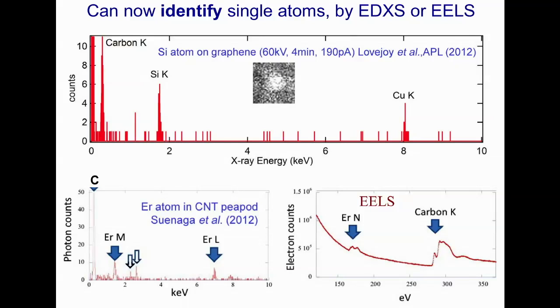The X-ray and energy loss spectra at the bottom were recorded from a specimen containing erbium atoms, each enclosed within a C82 fullerene molecule. These molecules were in turn encased in a single-wall carbon nanotube to form a so-called peapod structure. The purpose of the double encapsulation was to ensure that an erbium atom would remain long enough in the electron beam, about half a second, to give a visible erbium signal. Unfortunately, the 60 kilovolt electrons used to form a 1.5 angstrom probe are capable of displacing any atoms that are not strongly bounded to their surroundings, and putting the erbium atoms in a carbon cage minimizes this possibility of radiation damage.